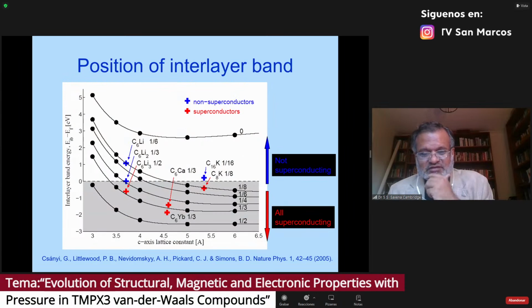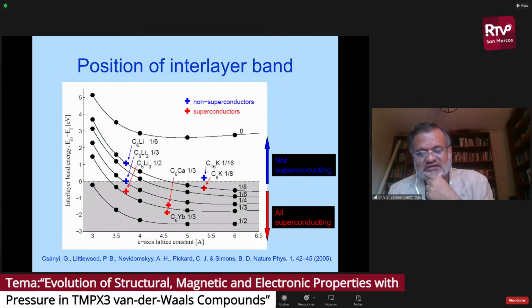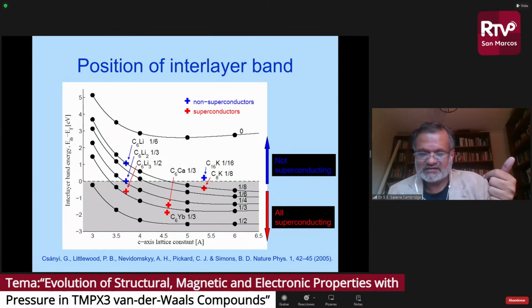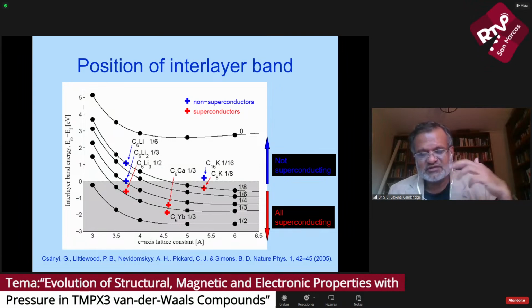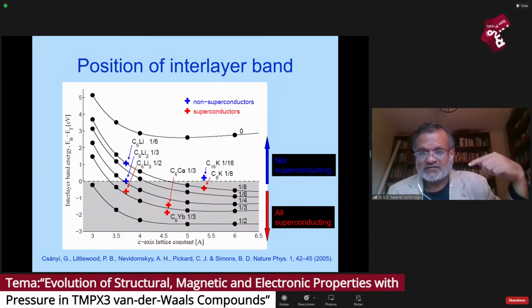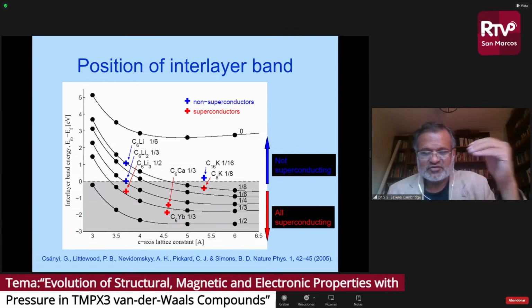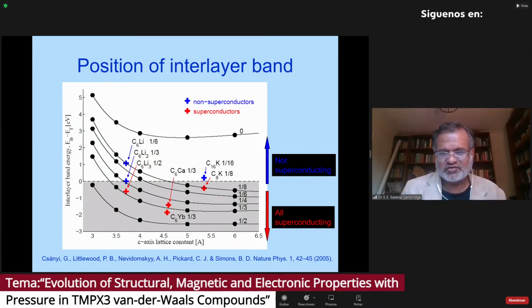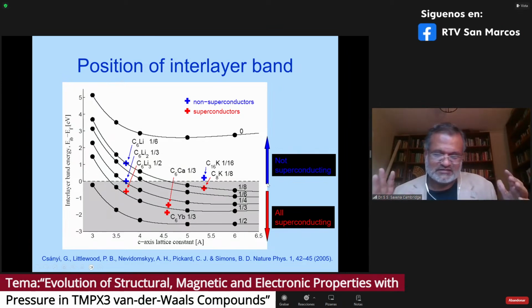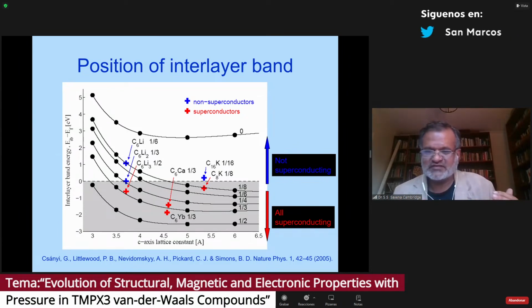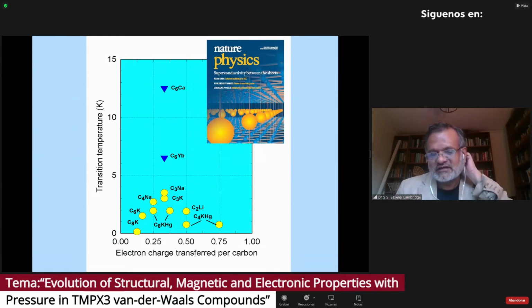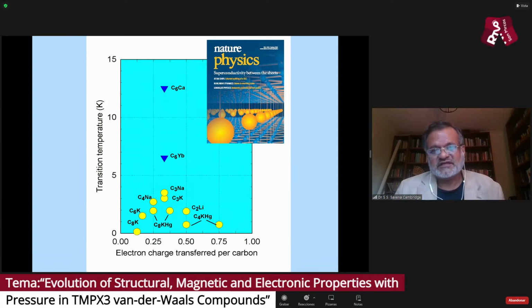And we worked quite closely with our theory DFT colleagues. What we found was a rather interesting phenomenon: in such a system, when you intercalate, your carbon pi star electrons hybridize with your intercalant d electrons and form what we call an interlayer state. And if the interlayer state gets occupied, you can see superconductivity. And if it's not, then you don't, and this was something they were able to capture in these calculations. So it's one of the few areas in superconductivity where, given empirical data, the DFT was able to more or less predict where you will find superconductivity in these systems, and that more or less holds. So this all became very big news, and it still holds a record in some sense for this type of materials.